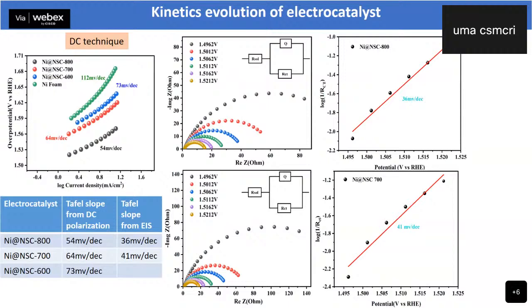Then the Tafel slope was calculated from the LSV as well as from impedance spectroscopy. And in both the cases, we found nickel 800 material with less value of Tafel slope, means good kinetic activity of the nickel 800 material.